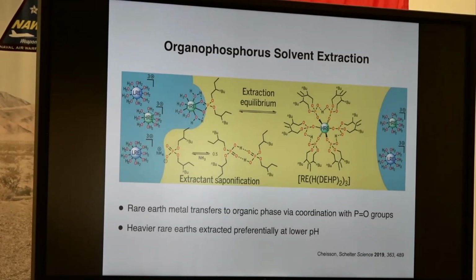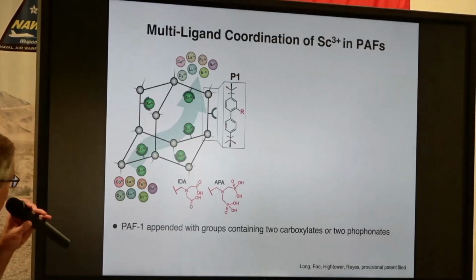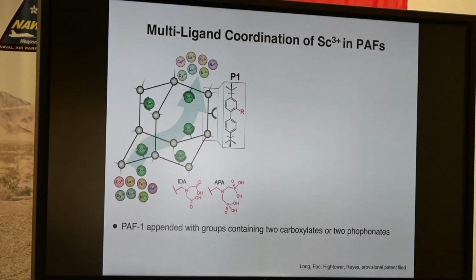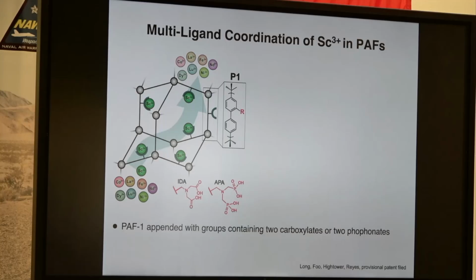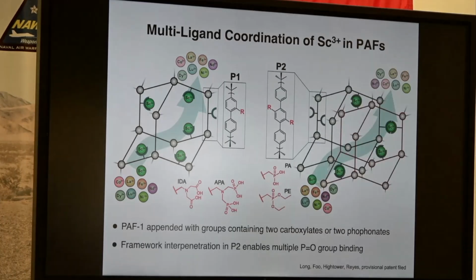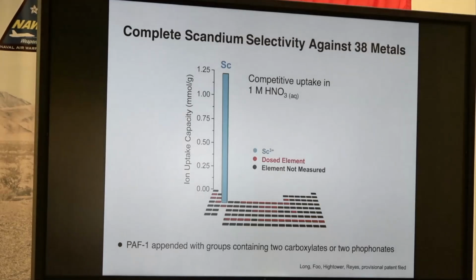And we'd like to do this at low pH because if we have to raise the pH a lot, that's a lot of waste chemical that you're pouring in. So we functionalized our PAFs with phosphonate ligands, and you want more than one phosphonate to be able to bind the cation. So there's two ways we approach this. One is we attached multi-phosphonate containing groups on the biphenyl in PAF 1. Or we can make a different PAF with terphenyl struts that actually forms an interwoven or interpenetrated network structure. And then monophosphonate groups from different networks can bind a single metal. Both of those strategies work.